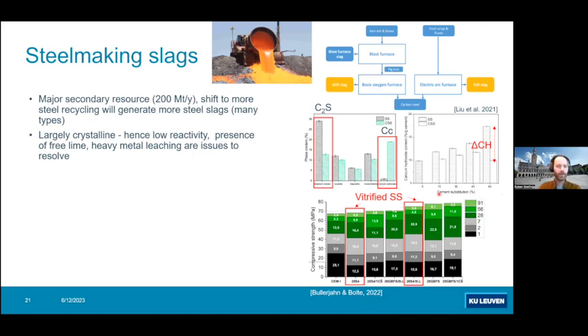The regular steel slag you will find is largely crystalline and has little reactivity, may have free lime, which is not of interest, and may disturb your hydration process or cause expansion. Some may have heavy metals that are leaching out. So all of these should be resolved.